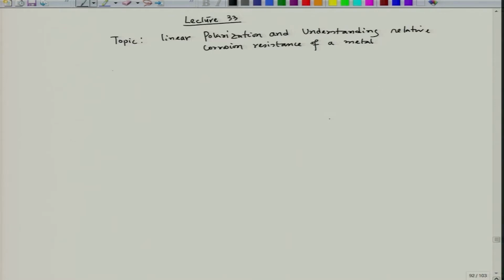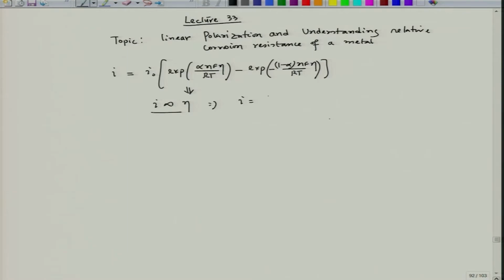So, now we started with this Butler-Volmer equation, I 0 exponential alpha nF eta by RT. This was the equation we started with, and then finally we achieved this relation where I can be written as nF by RT, I 0, eta. So, this is basically the constant which is giving a linear relation, and we have also seen that if we plot I versus over voltage, it will be linear.